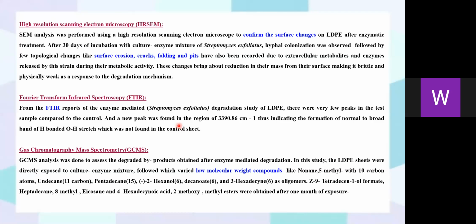to the degradation mechanism. FTIR: with the enzyme, there were very few peaks in the test sample compared to the control, and formation of new functional groups was also observed. GCMS also, under the culture enzyme mixture, it was observed that a large number of oligomers were present, inferring a reduction in the carbon atoms.